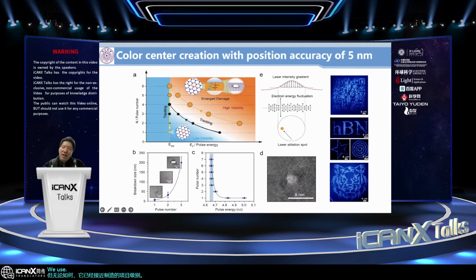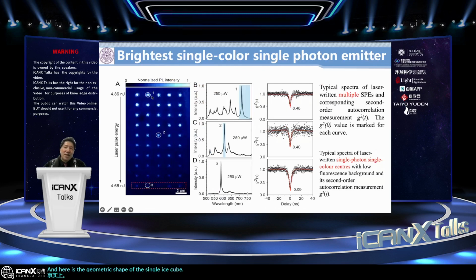We use such high level fabrication capability to produce very small size single photon sources. Actually, the single photon sources are related to the actual single atom defect. And here is the geometrical shape of the single atom defect. Here you can see when we reduce the light intensity to this level, from the spectrum and the second order correlation measurement, the g2 value becomes very small, smaller than 0.02. It means they are very high quality single photon sources.